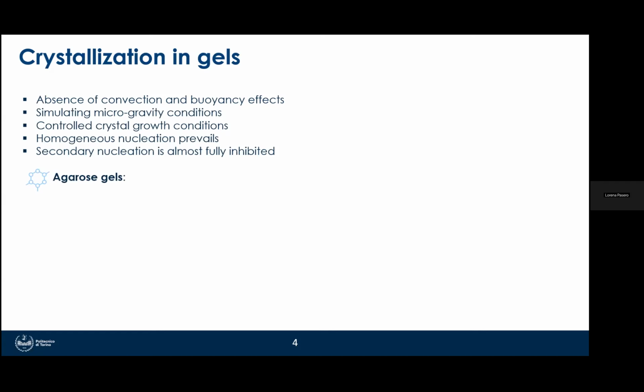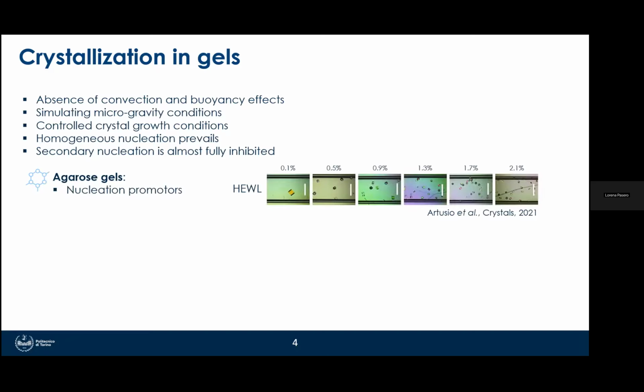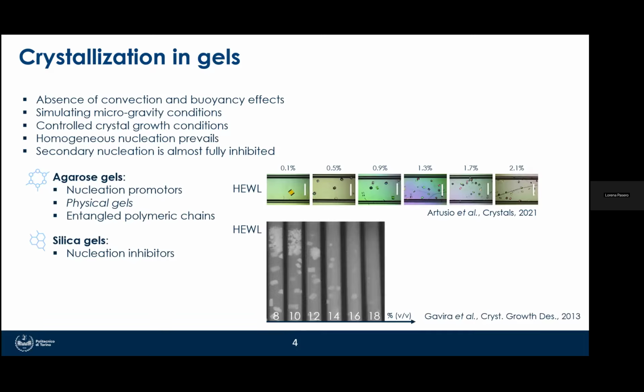But not all gels behave the same. As I said, we can use agarose gels, which are commonly known as nucleation promoters. They were, for example, introduced in a study from Artusio in 2021, where we saw that by increasing the concentration of agarose in the gel, there was an increased nucleation, so number of crystals, and these had lower sizes. These type of gels are called physical ones since they are formed by entangled polymeric chains, while the silica gels are a different type of gels which basically are nucleation inhibitors, as demonstrated by Gavira in 2013.